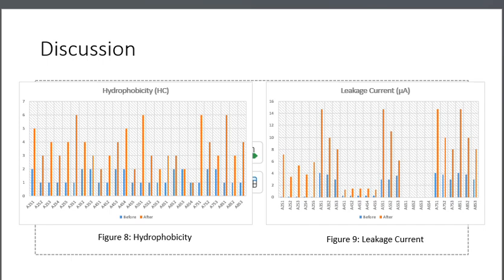First, regarding hydrophobicity, hybrid coatings showed better hydrophobic recovery after aging compared to pure silicone rubber. Second, leakage current values were significantly lower in hybrid filler samples. This improvement is linked to the coating's ability to maintain surface hydrophobicity and high surface resistivity. Additionally, diffusion of low molecular weight silicone molecules towards the surface helps restore hydrophobicity after contamination.